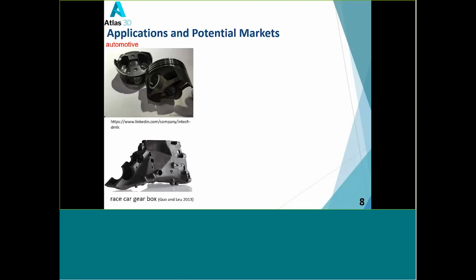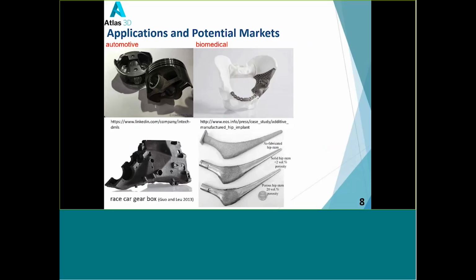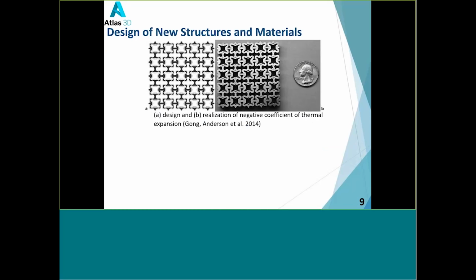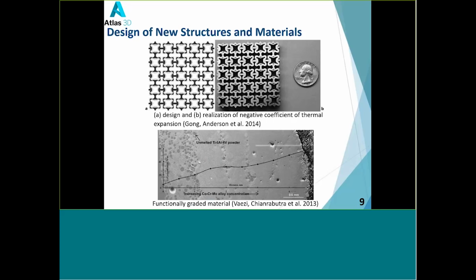There are lots of different applications for metal AM, including automotive, biomedical, and aerospace areas. You can also design new structures and materials with the metal AM method. Here, what I show you is that people use the metal AM method to build a structure with negative coefficient of thermal expansion. And we can also build new materials, or people even call it functionally graded material with the DED method. You can see that we can control the concentration of some gradient manually so that we can achieve the material properties.